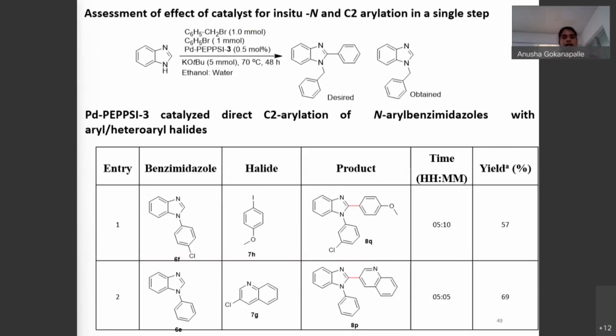Palladium PEPPSI 3 catalyzed direct C2 arylation of N-aryl benzimidazole with aryl and heteroaryl halides. We tried to extend the substrate scope, so we tried to prepare N-directly aryl substituted benzimidazole. But we observed lower yields when compared to N-alkyl substituted benzimidazole.